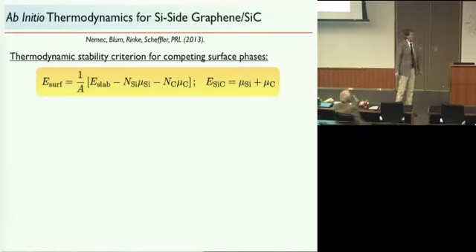We need to calculate the surface energy of different surfaces and find out which one has the lowest energy. We can calculate the total energy of a so-called slab model of the surface structure. And then we can calculate the surface energy by subtracting the energies of the individual atoms that make up this model, whether they come from the silicon carbide bulk or from elsewhere. So these are formal parameters here that stand for the energy of these atoms, which are known as chemical potentials in thermodynamics, the reservoir energies, if you will, of these atoms.